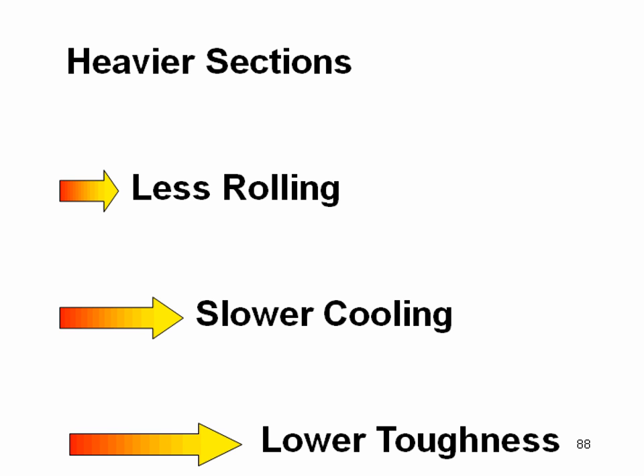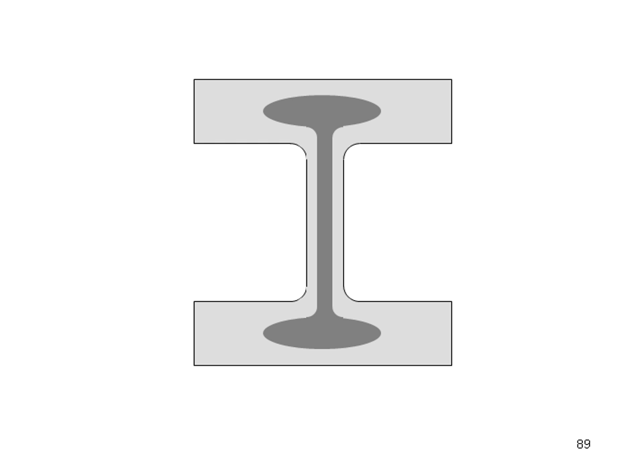Now let's take a look at the cross-section of one of these shapes. The steel for the Orlando project, and that was 30 years ago or so, was ingot-based. Most of our steel today is going to be continuously cast steel. So some of these details are a little bit different from current steel production practices. When you poured an ingot, the low melting point constituents, including carbon-rich regions, would segregate toward the center. Now, when you went to roll out the shape, what was in the center of the ingot always stayed in the center. And as a result, in our cross-section down through the center, there would be a core region that typically had higher levels of carbon.